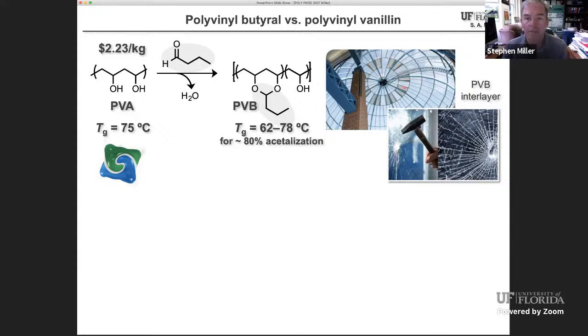And it is used in safety glass. Essentially, it provides a plastic, very transparent interlayer between sheets of glass. So in the case of breakage, the material tends to hold together. So we are interested in polyvinyl alcohol as a starting material, not really because it's bio-based yet, although it could be, but because it's water soluble. And as a water soluble polymer, it probably won't be a microplastic in the ocean. And there's a fair amount of evidence suggesting that polyvinyl alcohol could be biodegradable. It certainly won't float around in the ocean, because as I mentioned, it's fairly water soluble. It's certainly soluble at high temperatures, as you'll know if you ever put these little pouches in your dishwasher.